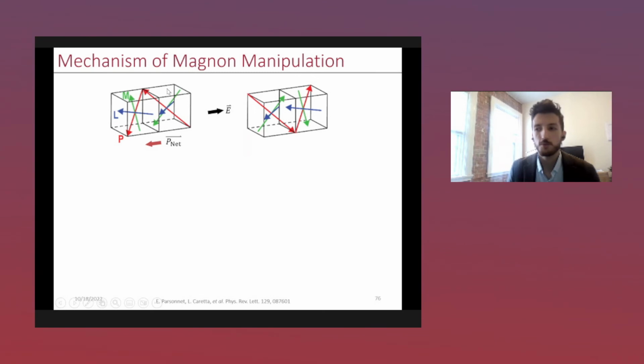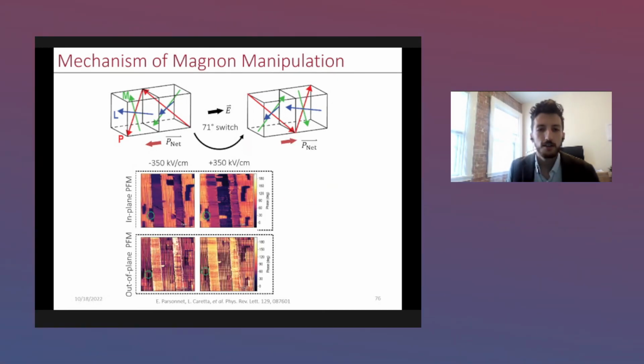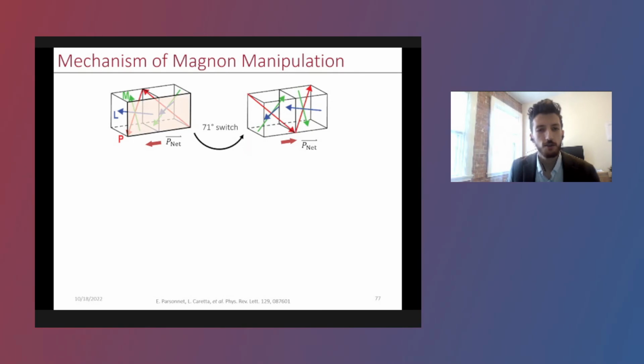This also comes with reorientation of the Néel vector and the magnetization as well. And if you look closely, you'll see that as we switch the polarization, the magnetic orientation, or the canted moment, goes from right to left to right. This is more easily seen if I just take a look at the cross section.